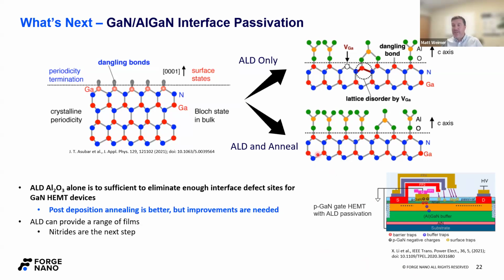But the idea here for me is that TMA water is great. It's a very common ALD process. It's the most common ALD process, but it might not be the right solution for gallium nitride, right? You might want a nitride interface. This gallium oxygen interface that's now created might be suboptimal. Okay, so this is an area that we think has a lot of potential for ALD in the future, kind of building on that acceptance of ALD in the field already.